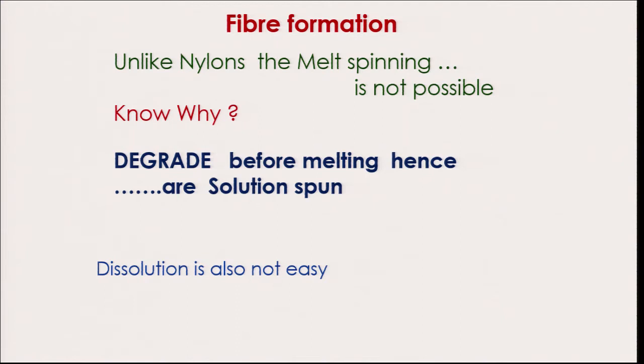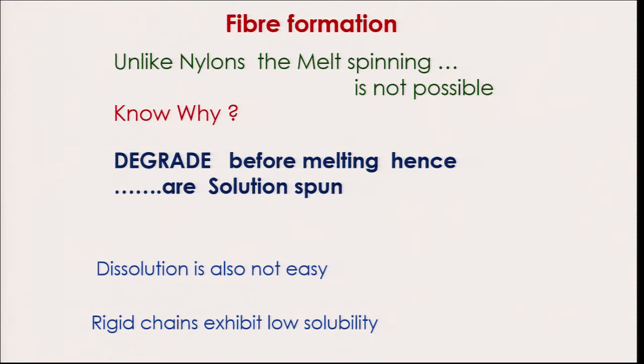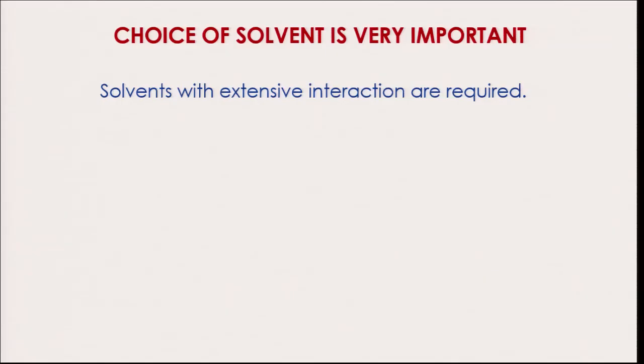Not only this, dissolution is not an easy task, because these structures are very rigid and also they have interchain interaction, the hydrogen bonding. Therefore, you need to use very special kinds of solvents to dissolve these rigid chains, which exhibit very low solubility. You need to use very strong solvents, which can overcome these interpolymer interactions and then interact with the polymer chains. And the choice of solvent plays a very important role.